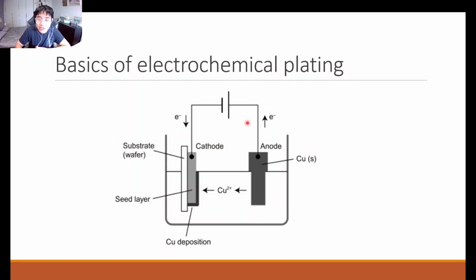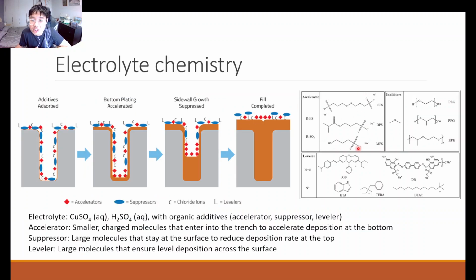So it's able to attract your charged accelerator molecules, which are able to enter into the trench, right? Because these molecules are small in size, they are not that big. Versus the other organic molecules, which are much bigger, like polymeric molecules or with very large, bulky aromatic groups. But over here, these molecules are rather small, so they are able to enter into the trench to accelerate the deposition at the bottom. Because of their charged nature, they are able to attract your copper ions, for example, to your wafer surface to accelerate the deposition that occurs at the base of the trench.